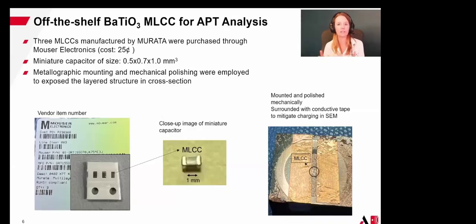And these are rated by size, so you can order different size devices, but you don't really know what kind of chemistry you're going to get because this could be a strontium zirconate, this could be copper-based electrodes. But here what we've done is actually taken one of these small devices, just about a millimeter cubed, and we want to probe the interior of the device. We can look at the interface between those electrodes, metal electrodes, and that ceramic capacitor.